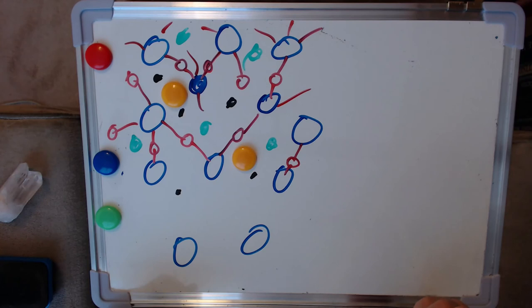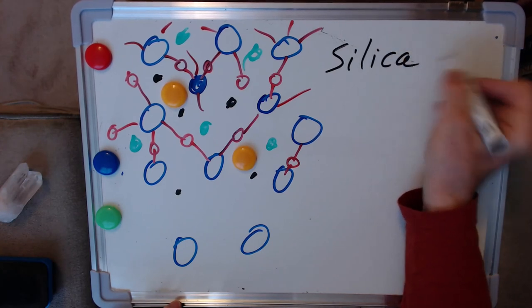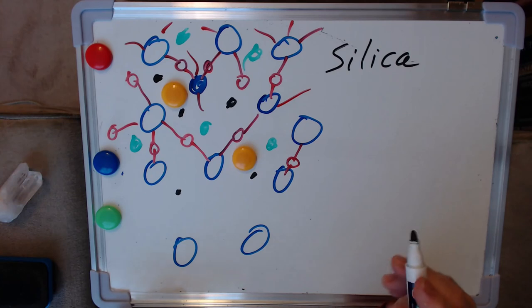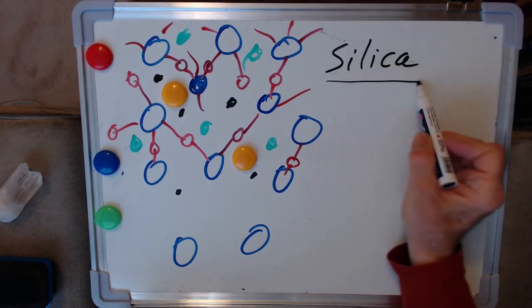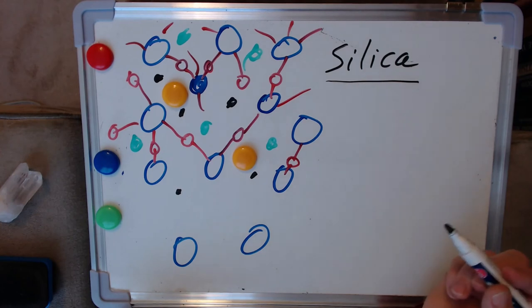So what we've ended up with then is a very rigid pure silica glass. And if I pinged that, you remember it rang very clear, and actually the vibrations carried on for a few seconds afterwards. And that's because it is this rigid structure. There's actually a very small number of ways in which the vibrations can be damped down in the glass.